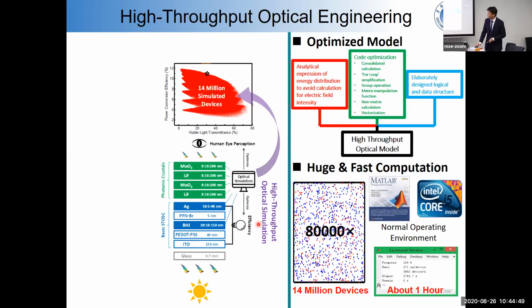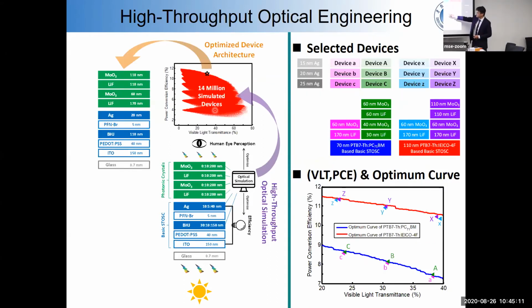And here I highlight the power conversion efficiency and the visible light transmittance. Each of these dots corresponds to a device architecture. The good thing is you can always find the maximum, the optimal curve, at the top. That means now we don't need to make 14 million devices. We only need to choose from this optimal curve. We choose several data points very close to this optimum curve, and then we make the device. These are the different thicknesses provided by the computational simulation.